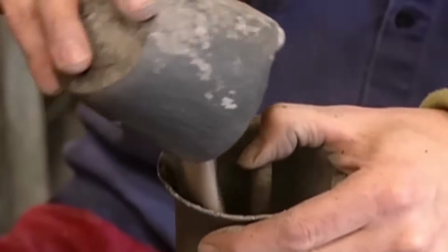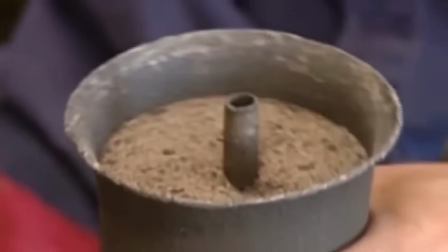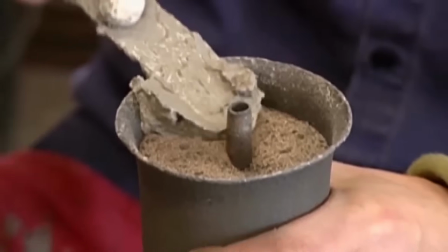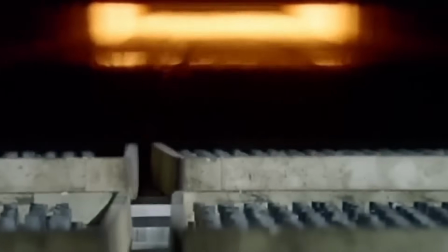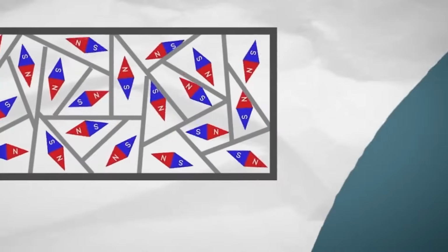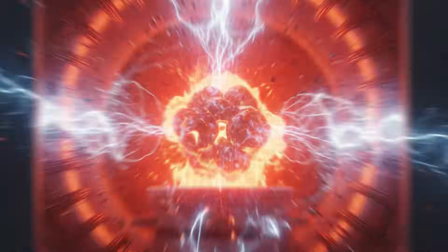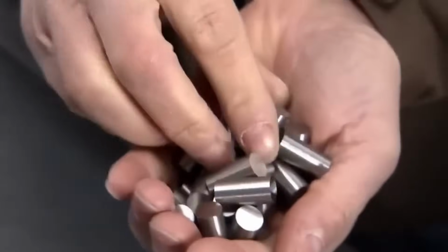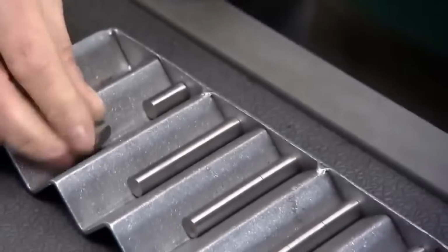The rings are loaded into a heat treatment tube filled with silica sand to distribute the heat evenly. The tube is sealed with heat-resistant cement to block oxygen, and then it's pushed into an electric furnace. Inside, the rings heat up to between 900 and 1100 degrees Celsius until they glow red hot. This step improves the internal microstructure, relieves stress, and prepares the material for magnetic alignment. Even though the rings now have their final shape, they still don't act like magnets.